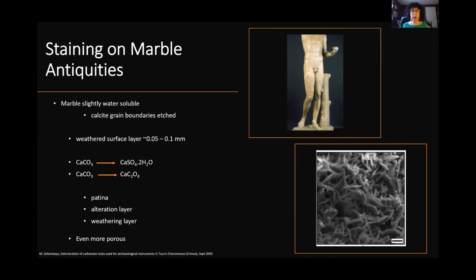What's chemically happening on the surface of the marble when it gets weathered is that it's being transformed from calcium carbonate into a hydrated form of calcium sulfate that's known as gypsum, or to another mineral called calcium oxalate. Both of these minerals are larger than calcium carbonate, and so the surface actually expands and becomes even more porous.